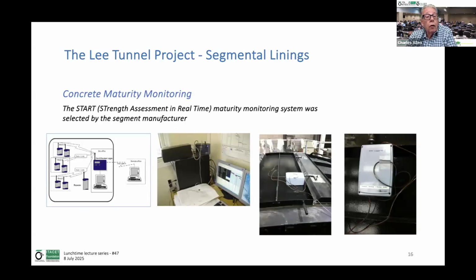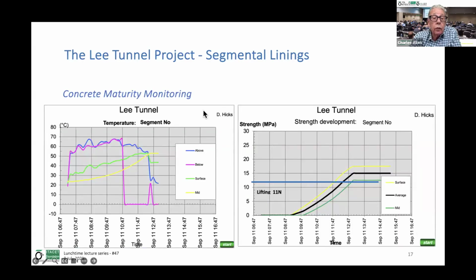They used a concrete maturity system called the START system, strength assessment in real time. And this works on having thermocouples inserted in the concrete, and then you have a little radio transmitter. This was housed in a plastic case, and that transmits the signal, which is temperature and time at 10-minute intervals, and that goes into a data logger in the segment factory office, and from that you can download strength and temperature. Here you can see the temperature.